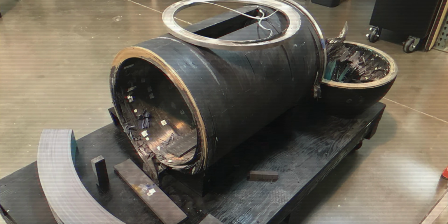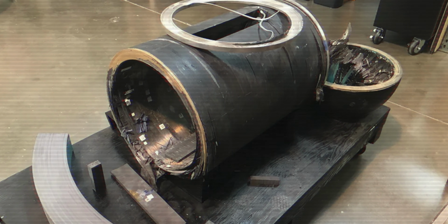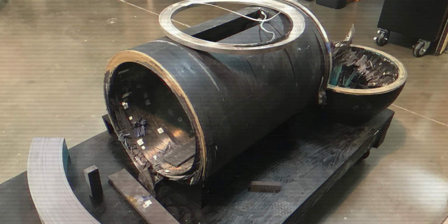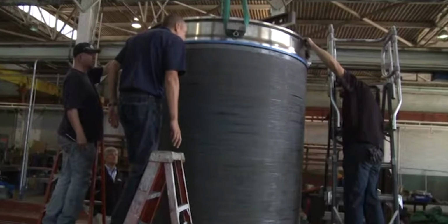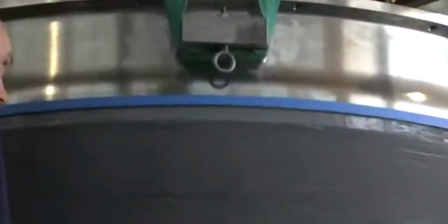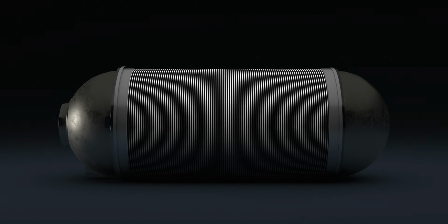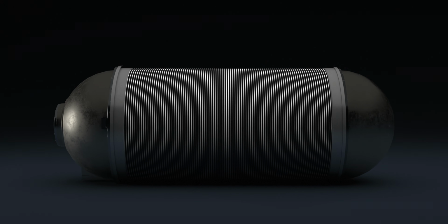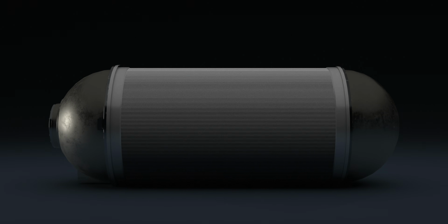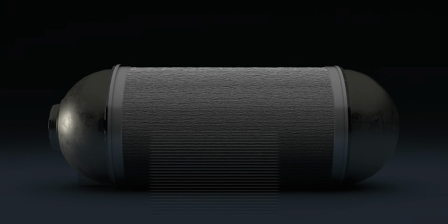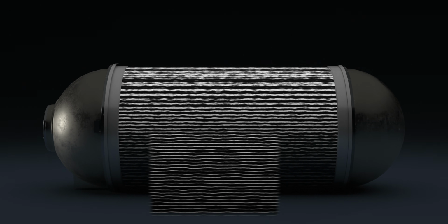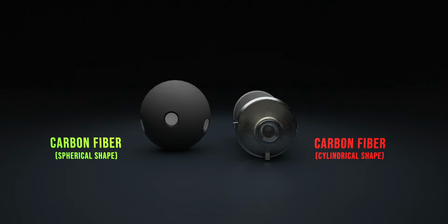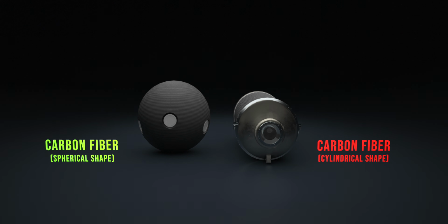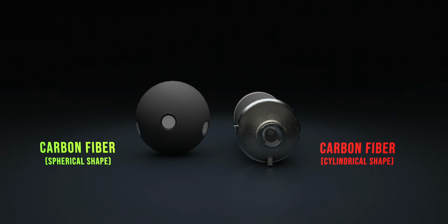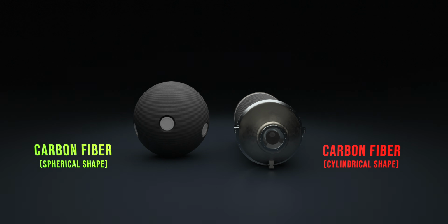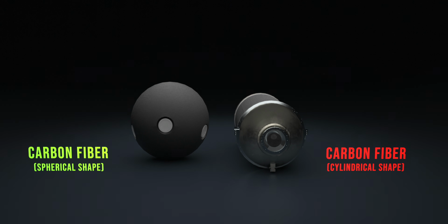The geometry of Titan's pressure hull further complicated this behavior. Unlike a sphere, a cylindrical pressure hull does not distribute compressive loads uniformly. Fibers wrapped around the circumference of the hull carried the external pressure efficiently, but the longitudinal fibers terminated at the titanium end caps, where they experienced complex stress concentrations. Those non-uniform load paths made the composite laminate more sensitive to manufacturing defects and progressive damage than an equivalent spherical pressure hull, in which compressive loads are distributed much more evenly.